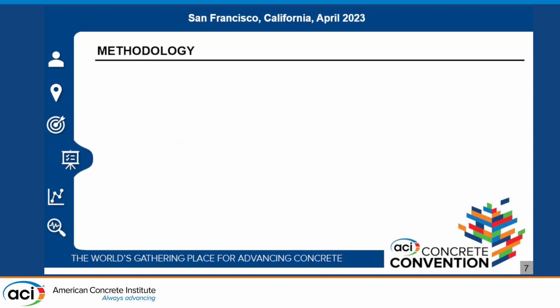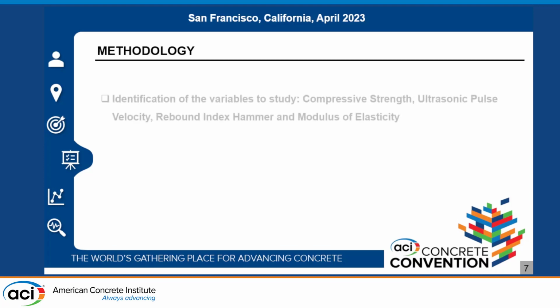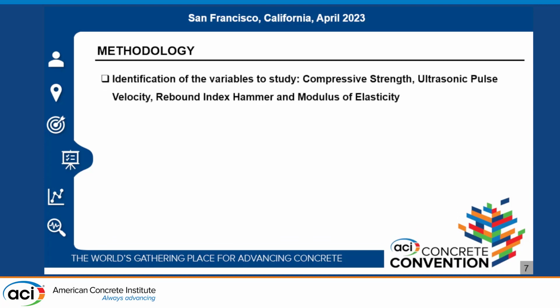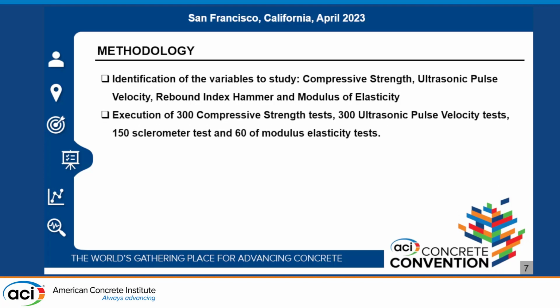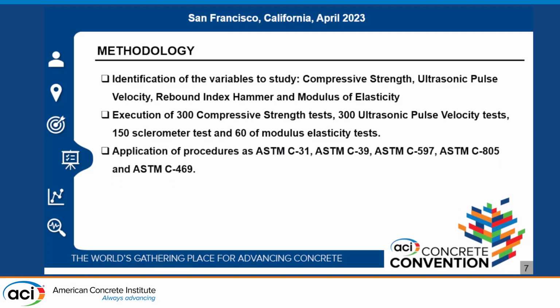The test methodology implemented consisted of four parts. First, identification of variables to study: compressive strength, ultrasonic pulse velocity, rebound hammer index, and modulus of elasticity. Execution of 300 compressive strength tests, 300 ultrasonic pulse velocity tests, 150 Sclerometer tests, and 60 modulus of elasticity tests. Application of procedures such as ASTM C31, ASTM C39, ASTM C597, ASTM C805, and ASTM C469, and the analysis of the effectiveness of each model found.